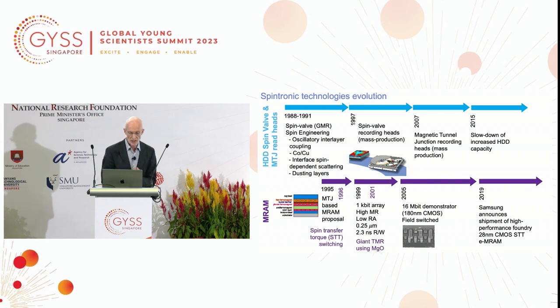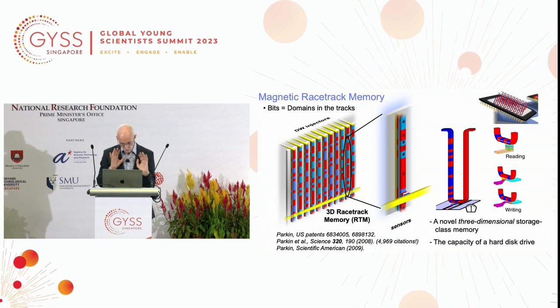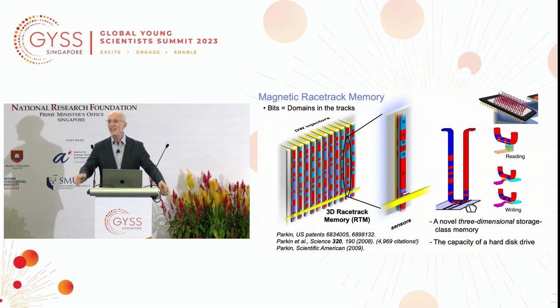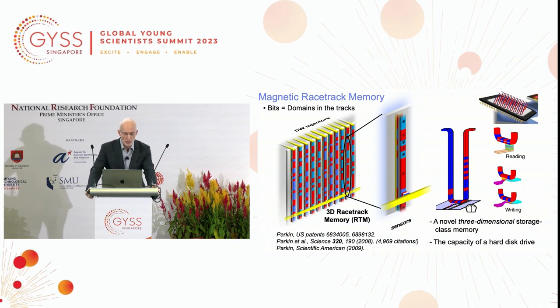On the other hand, surprisingly, for the spin valve sensor, using the physics I discovered in 1988 to 1991, IBM could incorporate that into magnetic disk drives in just 6 years, which is remarkable, allowing, as I said, a 10,000-fold improvement in the capacity of magnetic disk drives. So I want to now discuss briefly another memory that I'm even more excited about, and I actually also proposed this in 2002. So now it's 20 years later, and not yet available, but we believe, or I believe, it's on a path to application.